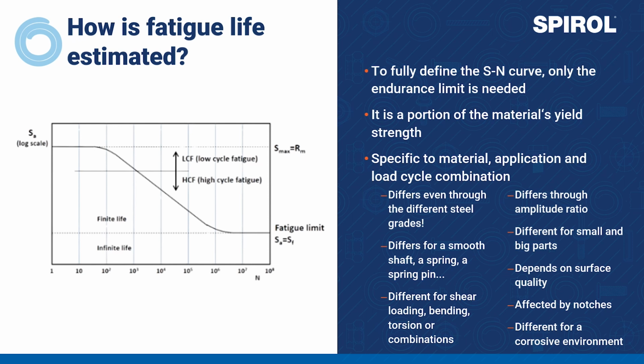And for example, it's different for all grades of steel. It's different for the application type. It's different for the type of stress created by the load, be it shear, bending, torsion, tension, or combinations thereof. The amplitude ratio of the pulsating force makes a difference. The size of the part also affects the endurance. Surface quality and presence of any notches is another factor to consider, as well as any corrosion that might be weakening the part over time.